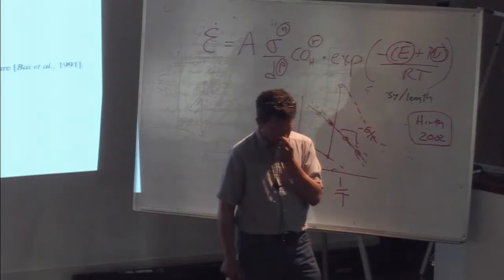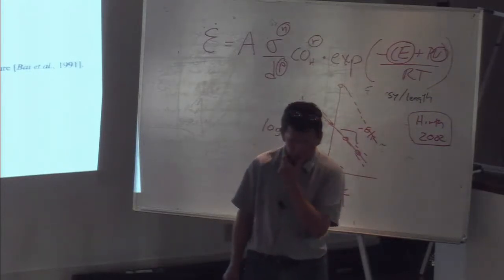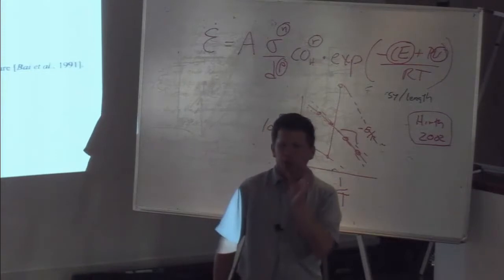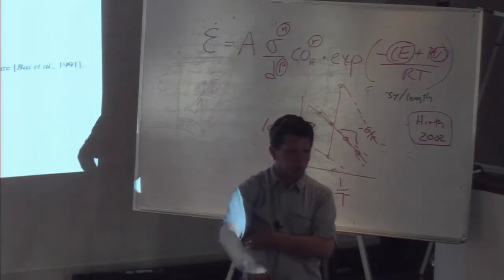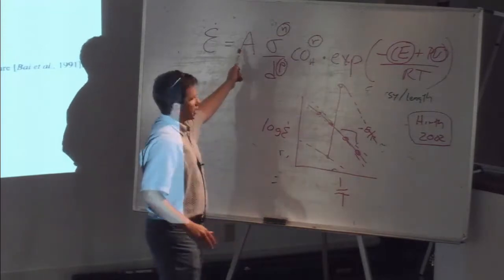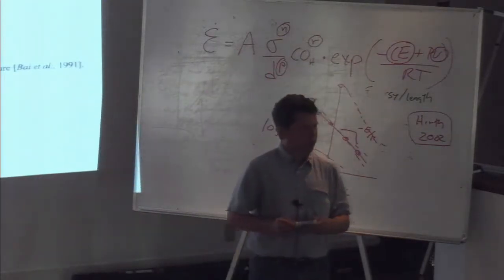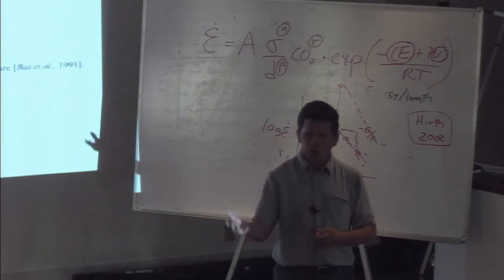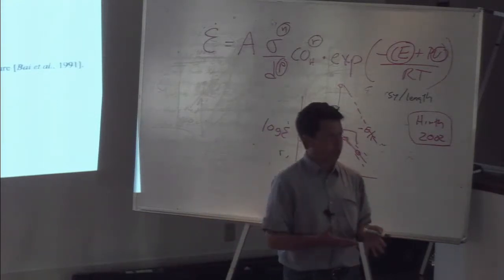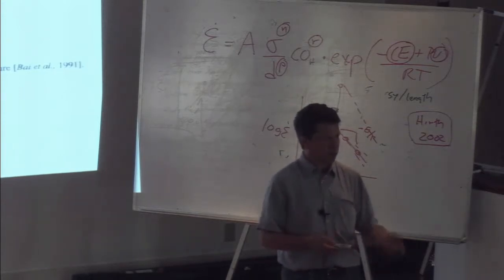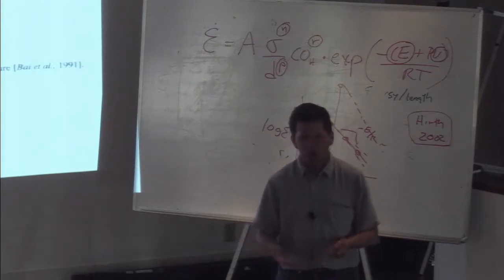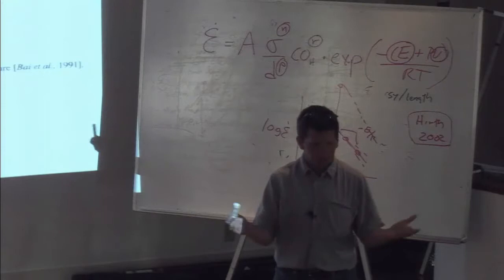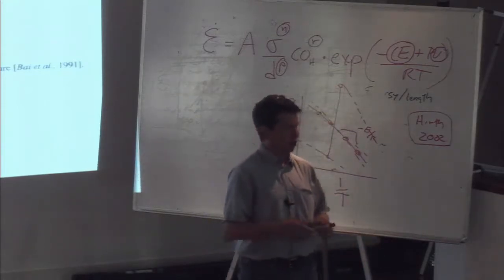But one other thing, and this is also a true story, and I'll protect the names to protect the guilty. There was a very prominent review paper that tabulated all of these parameters, and they gave the A in gigapascals instead of megapascals. And so you take this number, which is 3 orders of magnitude, to an exponent of 3. So it gives you answers, and maybe part of the origin of what Torsten was talking about, answers that are 9 orders of magnitude wrong. And so people were like, wow, convection's not happening. This flow law is clearly wrong.